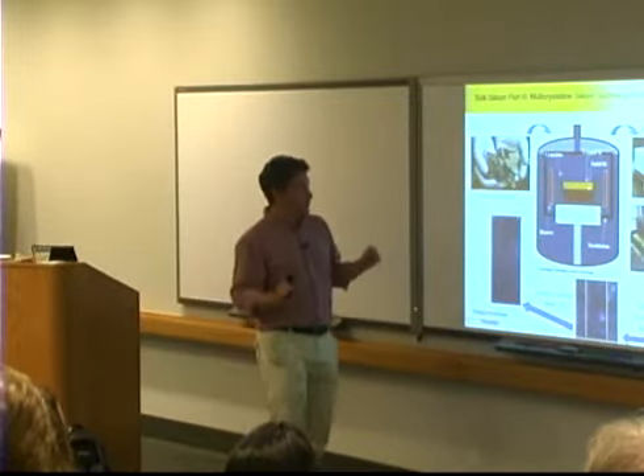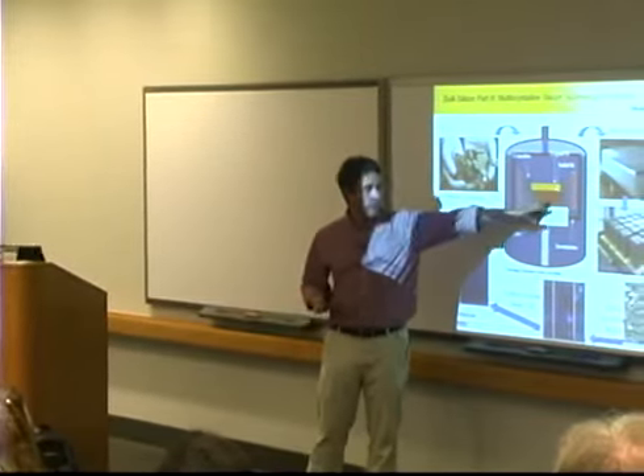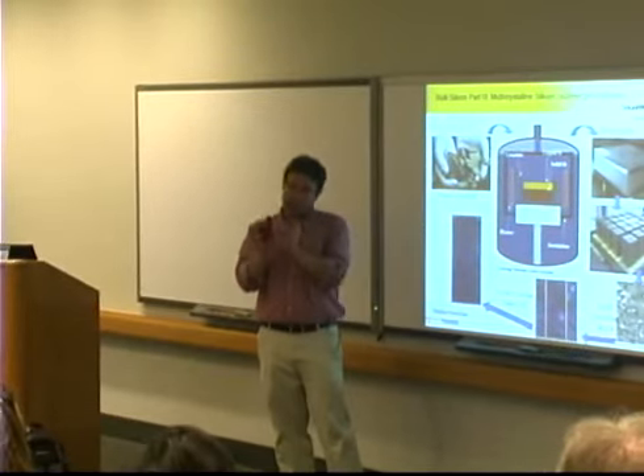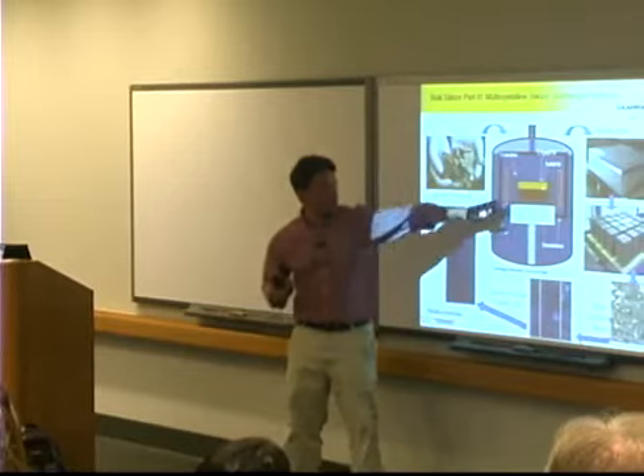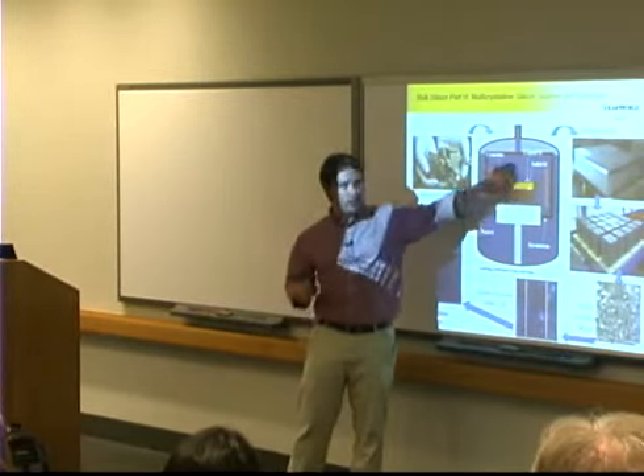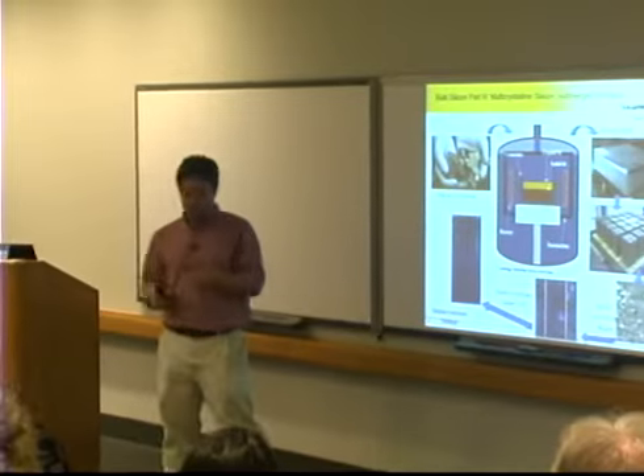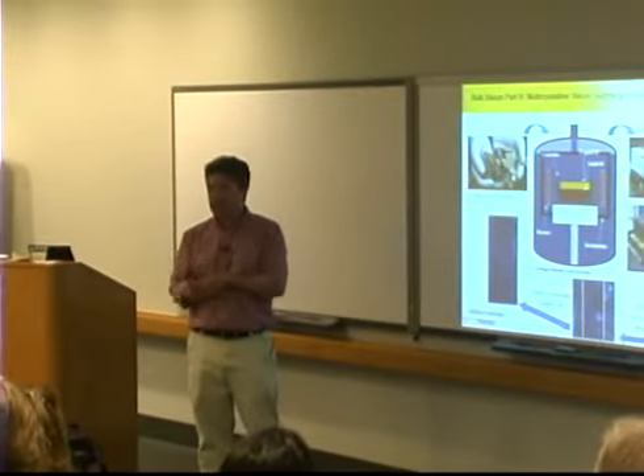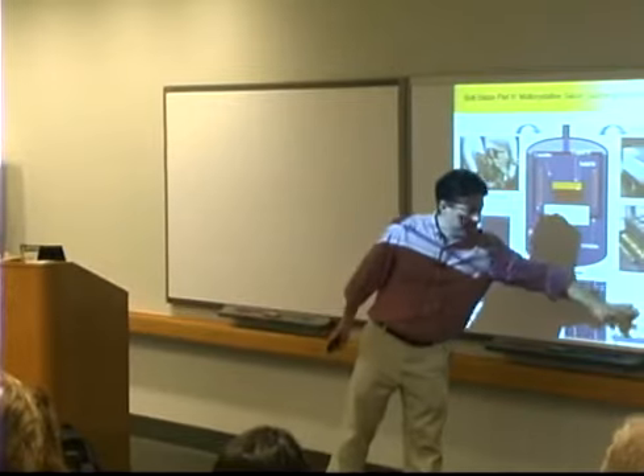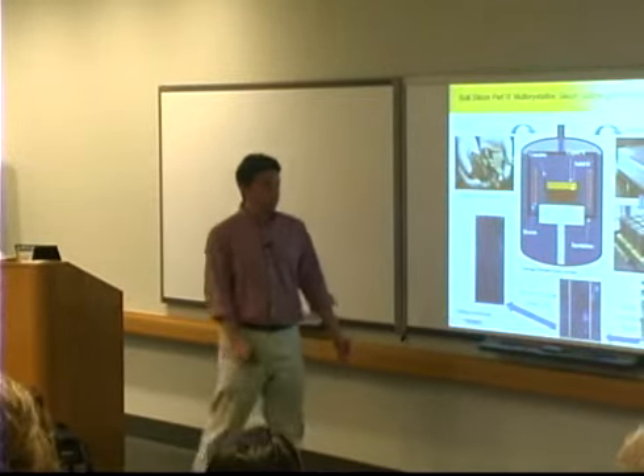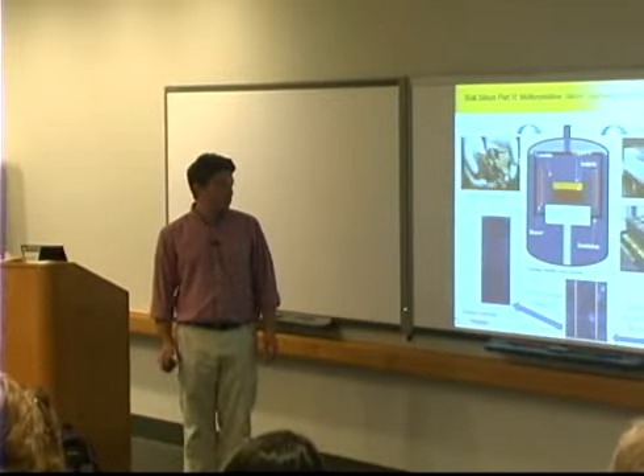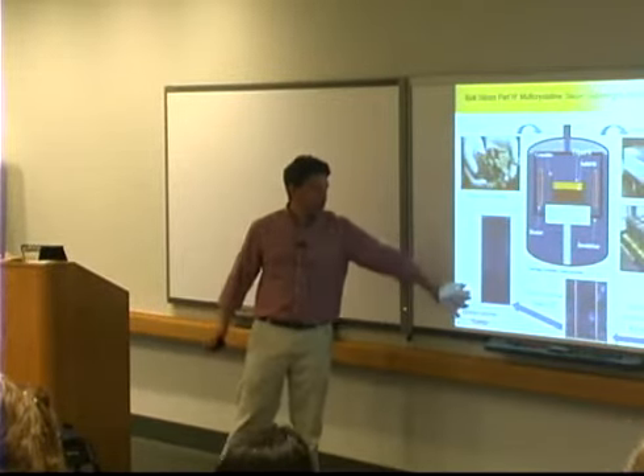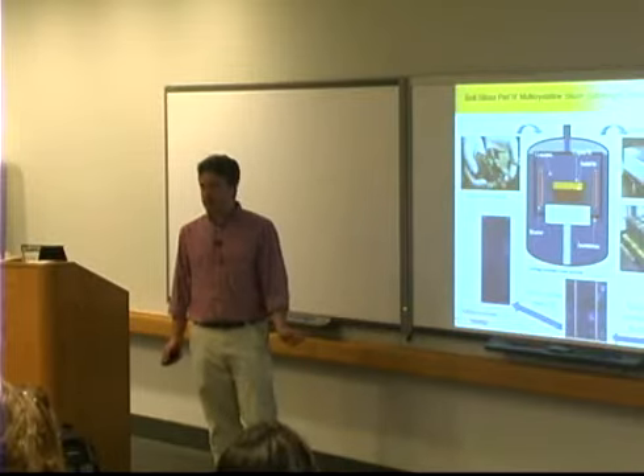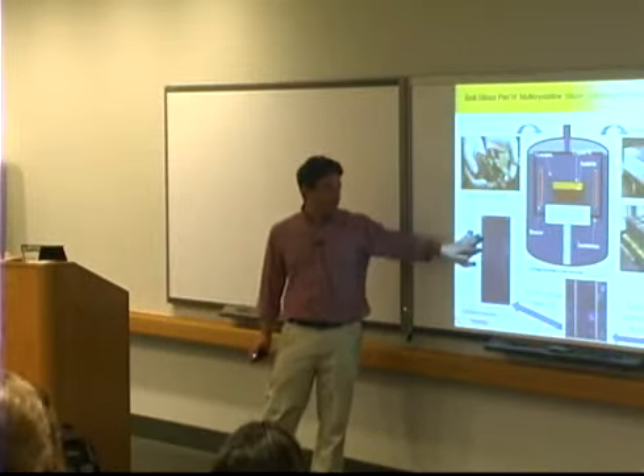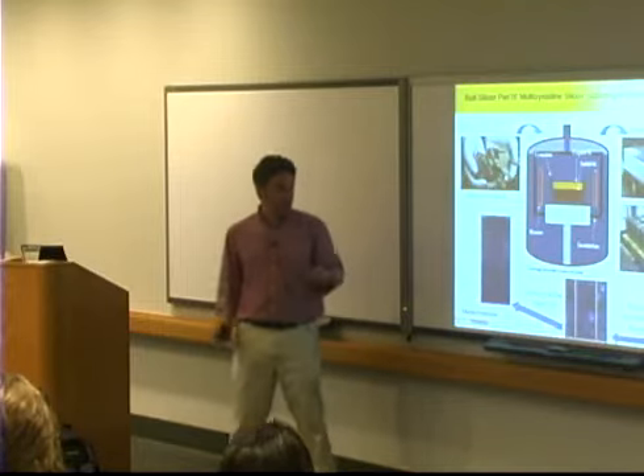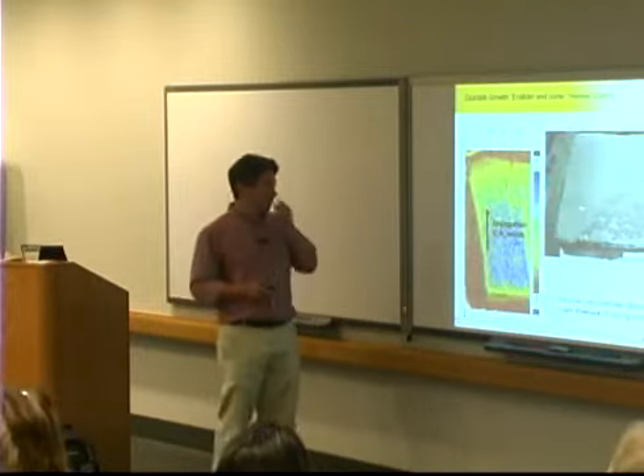There's no attempt at controlling crystallization, so you get random nucleation of small crystals at the bottom. You get competition between those crystals early on, and then you get these fairly steady columnar crystals, typically somewhere between maybe 5 millimeters and 20 millimeters in size. Here's a typical wafer. That's a 5-inch wafer for context. And when you make a solar cell and a module, you definitely get lower efficiency than CZ, based largely on structural defects, grain boundaries and dislocations, but also on purity.